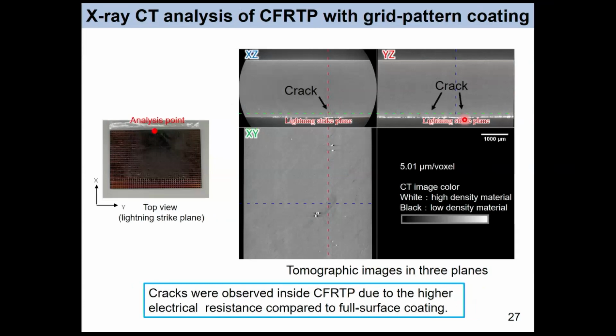At last, this is the grid pattern coated case. We can see a crack occurs in this case. The metal mesh can reduce the damage to CFRTP, but a little crack was observed in the sample. This is probably because of the low electrical conductivity of the CFRTP grid pattern coating. So we have to improve the electrical conductivity of the grid type: improve the coating density of each line, improve the electrical conductivity of each line, and also consider parameters such as grid spacing and grid width.